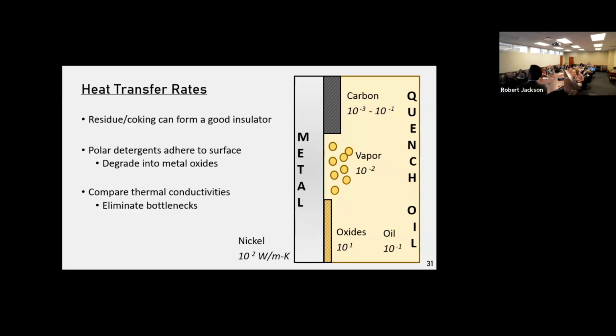So the level of additives we put into the quench oil generates three different kinds of regimes of surfaces. We've got a carbon layer or a char layer, which could be very dense and actually thermally conductive, or it could be quite insulating, almost like an aerogel. The vapor is quite unfavorable. So what we want is sort of an oxide layer. We have certain inorganic metal species in the quench oil, and they decompose into, rather than this carbon, a very dense, nice oxide layer that transfers heat not as rapidly as the metal, but much faster than a carbon aerogel or a vapor barrier layer. So we can control that with things like detergents, surface active materials. And then we also want to make sure that we have good oxidative stability, so we can do the whole process all over again.